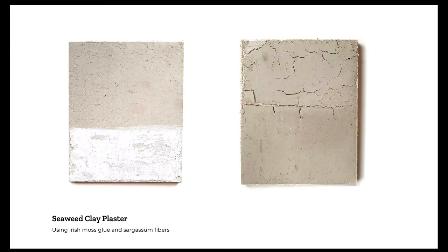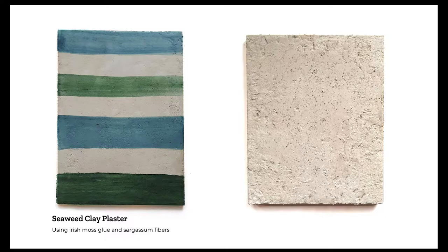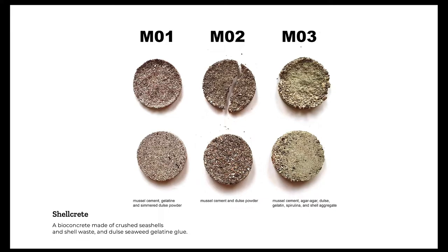This was my attempt to find a ratio that works with a local Dutch species. I also experimented with using sargassum as a fiber in the plaster instead of hay. I found that the clay encapsulates the sargassum and prevents it from rotting — typically you don't want to use seaweed as a fiber in construction because it tends to rot, but when you encapsulate it in clay, the clay sucks all the excess moisture out of the seaweed. After about eight months it's totally fine in my apartment, so I feel comfortable saying sargassum can be used as a fiber in this circumstance.